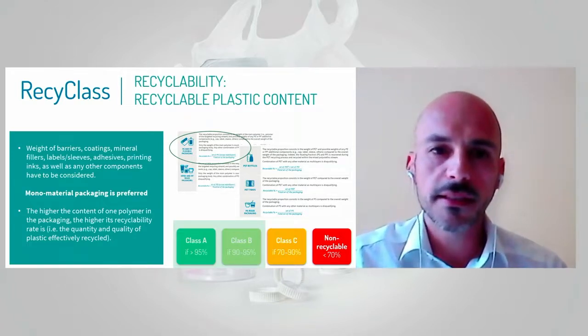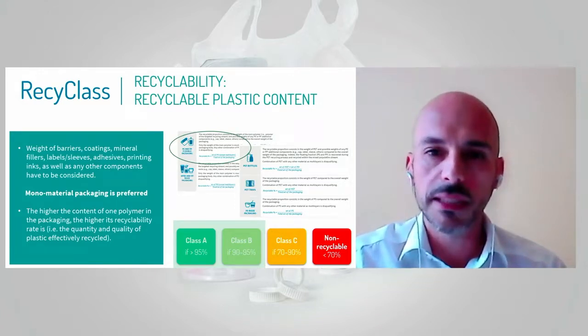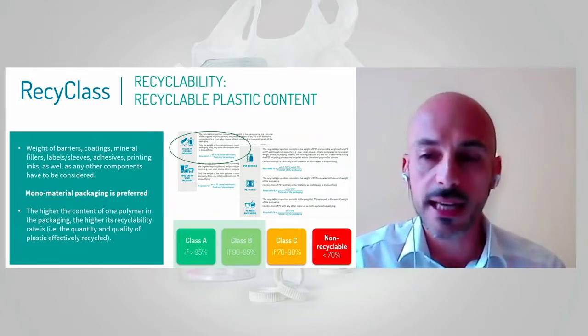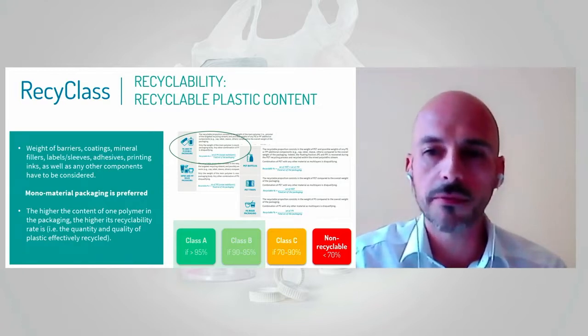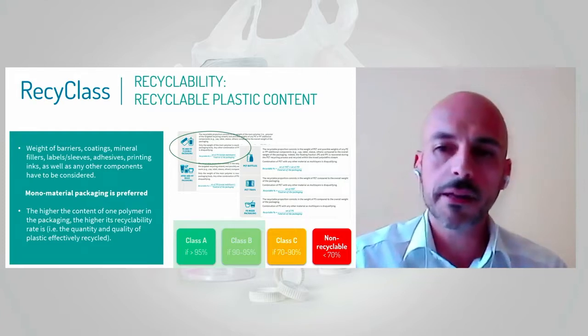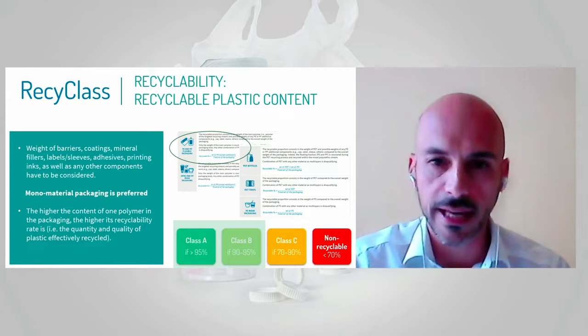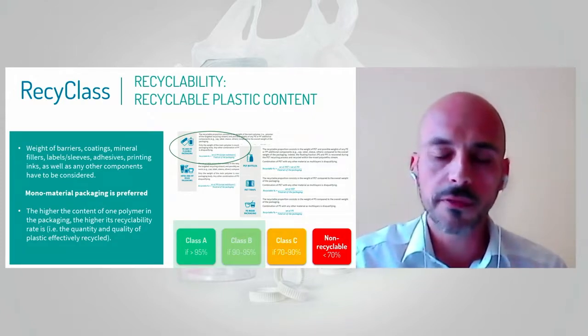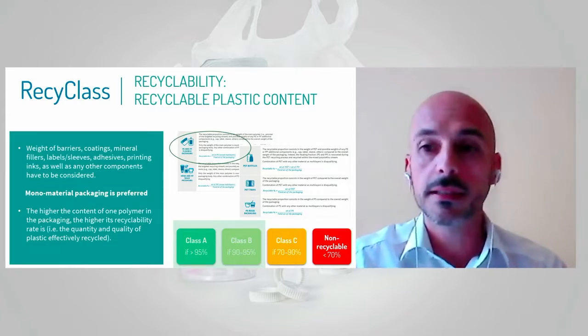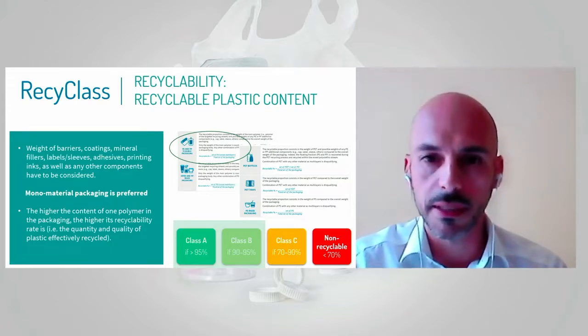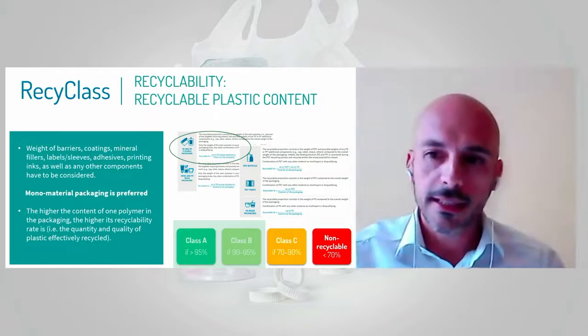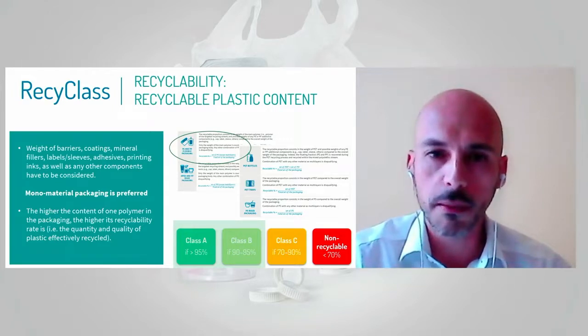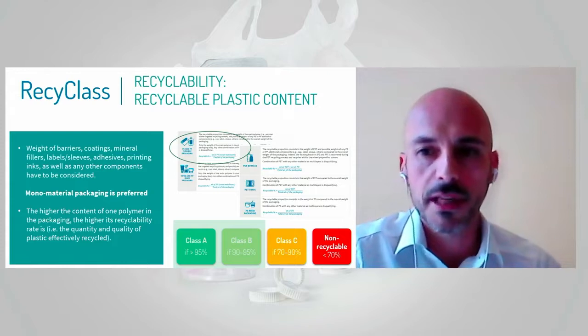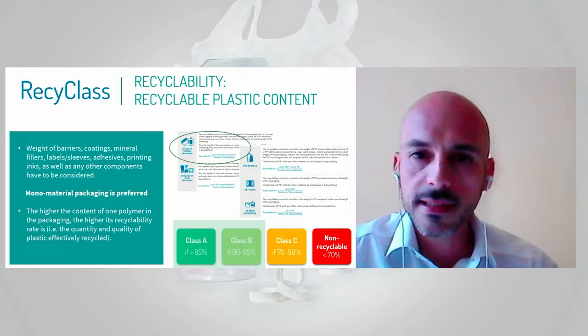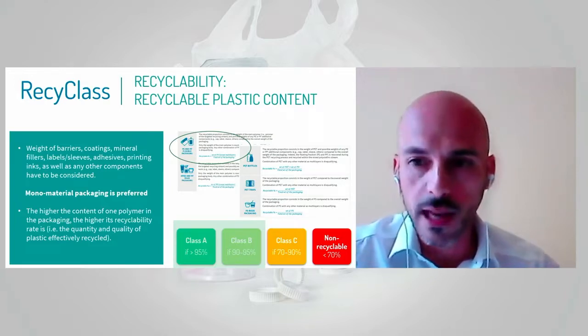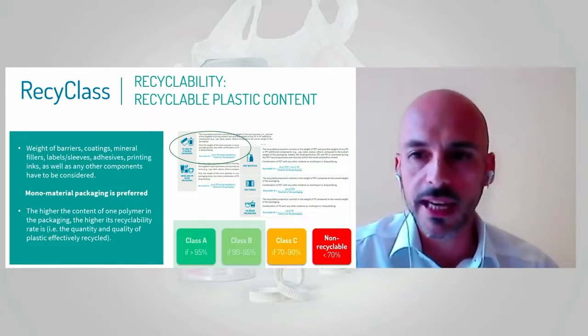And in Recyclas, this is important to define the starting recyclability class of the packaging, where if the packaging has a concentration of polypropylene, talking about polypropylene flexible, higher than 95% by weight, this is the prerequisite to start the recyclability assessment with the class A. If the packaging is less concentrated in polypropylene, for example, between 90 and 95% by weight in polypropylene, this is the prerequisite to start the recyclability assessment with the class B. If the concentration is still lower, and this is under investigation because the Commission is probably looking to have on the European market just packaging with a higher than 95% concentration of the target polymer. But in any case, with Recyclas, the recyclability assessment will start with a lower class ranking, meaning that the packaging will be very difficult then to recycle.